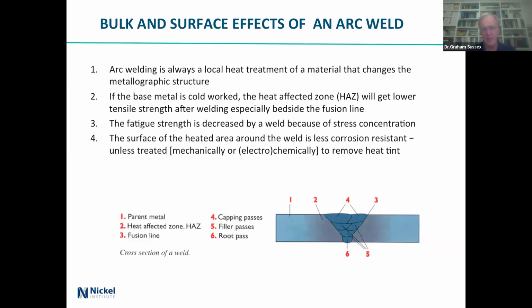you treat it, either abrade it or electropolish it or chemically pickle it to remove the heat tint. If you're going to mechanically abrade it, then don't get it too rough, because there is a strong correlation between corrosion and surface roughness, and the break point is about 0.5 micrometer Ra.